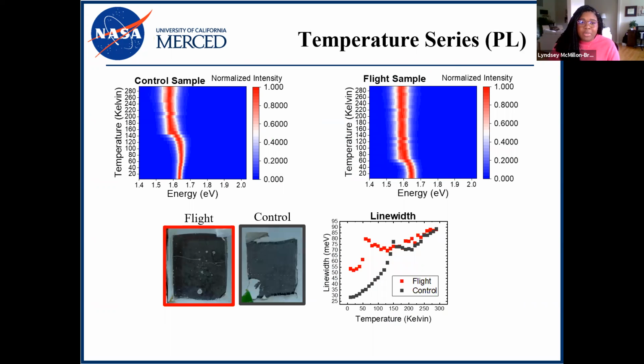So here I want to share some temperature-dependent PL data, and our excitation wavelength was 532 nanometers. At each temperature, we're plotting the entire spectrum. The ground control sample here shows that at about 148 Kelvin, we're jumping to the higher energy emission. And this right here is evident of a transition from tetragonal to orthorhombic crystalline structure in the perovskite. Now, the MISSE flight sample shows that transition happens at much lower temperatures, actually at about 55 K.